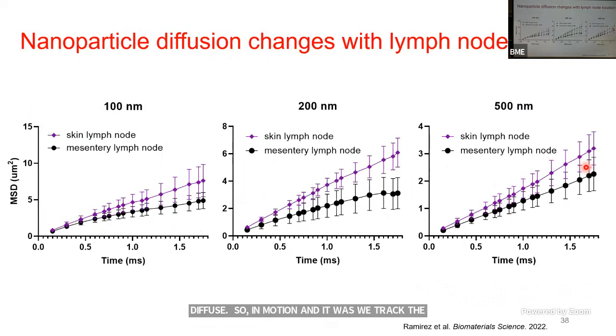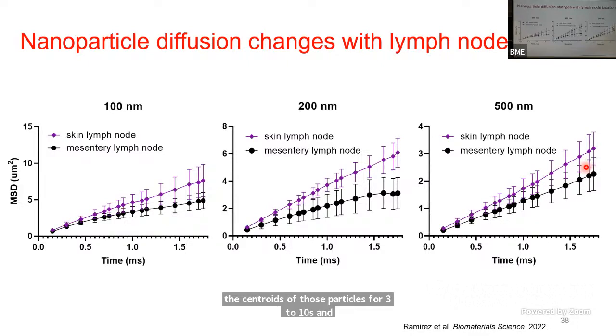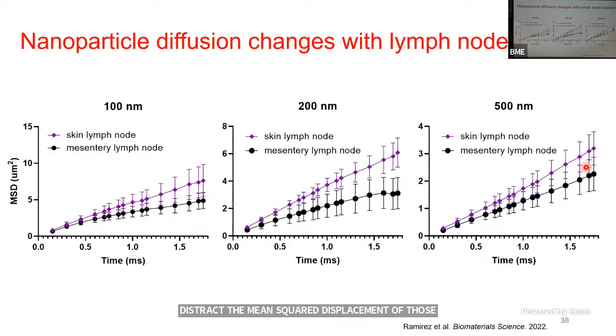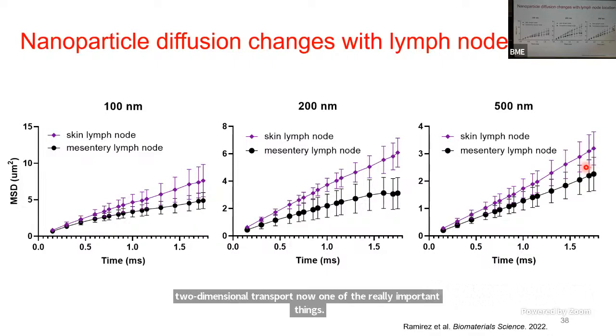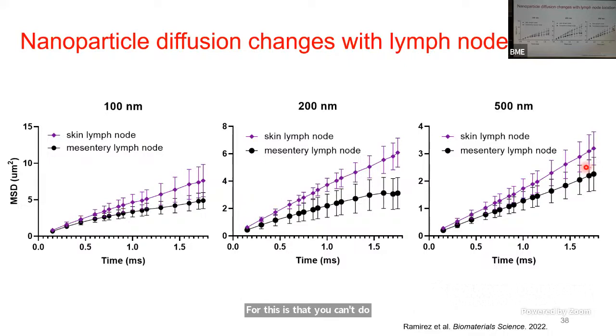And really interestingly, we actually found that nanoparticle diffusion seemed to be slightly reduced in those mesentery lymph nodes compared to the skin draining lymph nodes. We honestly had no idea what we were expecting. So it was great that we even found something that was different. And so now we're starting to think about, well, what is going on here? And also trying to understand, okay, when we're comparing some of these, you see a little bit of difference and it seems to vary also by particle. So trying to think a little bit more about pore size as well here.